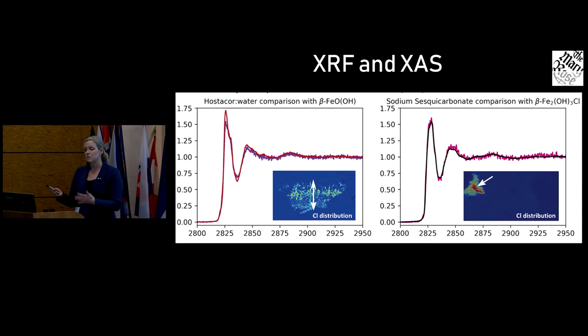For some of the treatments, you'll see that you'll just get little inclusions inside. And when we look at the spectroscopy of that, you actually get different phases. So sometimes it's something called akaganeite, which is a very typical, very damaging corrosion product. In other cases, particular inclusions inside, you'll find that it's a precursor to that product, and it will only form given the right conditions, the right solutions, the right pH, things like that.